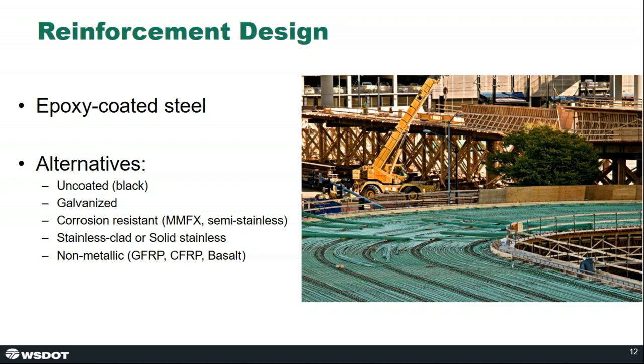And that coating is intended to delay the onset of corrosion by preventing air and moisture from coming into contact with the steel surface. And there's a number of other alternatives out there: galvanized bar, semi-stainless bar, stainless clad bar, or non-metallic bars. We've got a couple test projects looking into galvanized steel and MMFX, which is a proprietary semi-stainless type steel, to try to gather some cost data on this bar to find the right cost benefit.